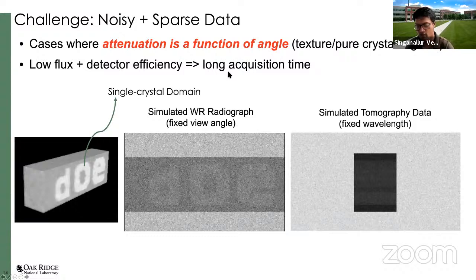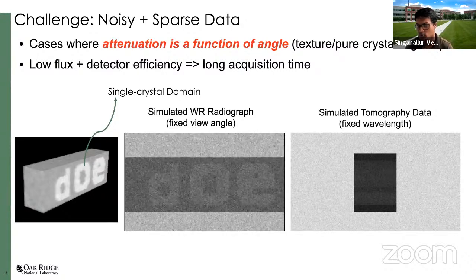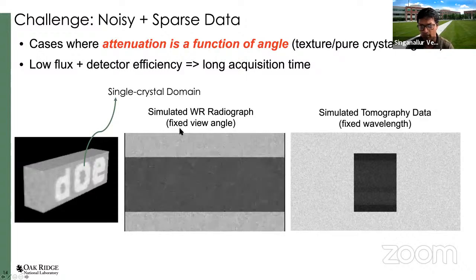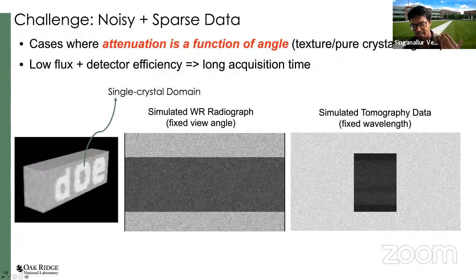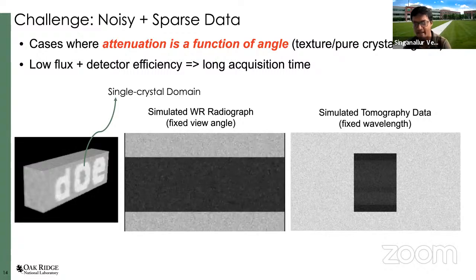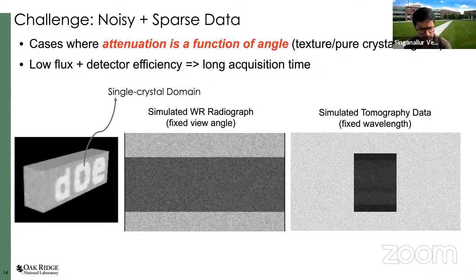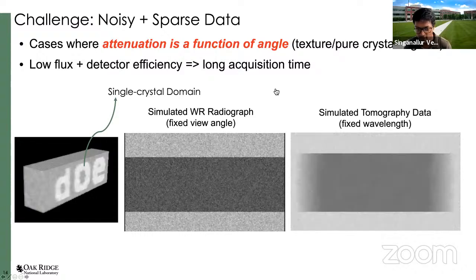The other challenge with wavelength resolved neutron CT is that these are extremely time-consuming measurements. So the flux, the detector efficiency and low flux in neutron CT make it very challenging, and it can take a very long time. For example, we did a CT recently, and it took 3 days to acquire about 30 projection angles. This is an extremely time-consuming measurement, further complicated by the fact that when you're looking at crystals, you can start seeing diffraction. And what you're going to see now, in simulations, is that when you're rotating the sample, at certain angles it flickers. The flickering occurs because the attenuation suddenly changes.